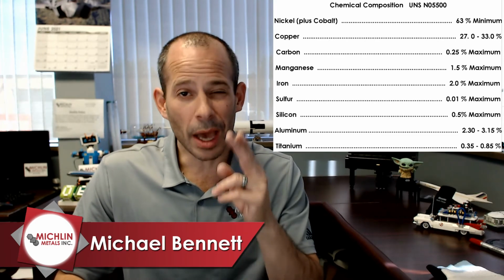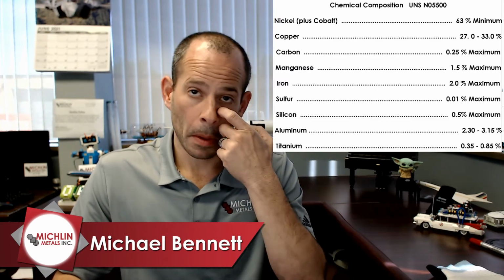We got carbon, 0.25% max. We got manganese at a 1.5% max. We have iron at a 2% max. We got sulfur at a 0.01% maximum. Silicon, 0.5% max. Aluminum is 2.3 to 3.15%. And titanium, lastly, is 0.35% to 0.85%. So there we go. Now, the density is 0.305 pounds per cubic inch.